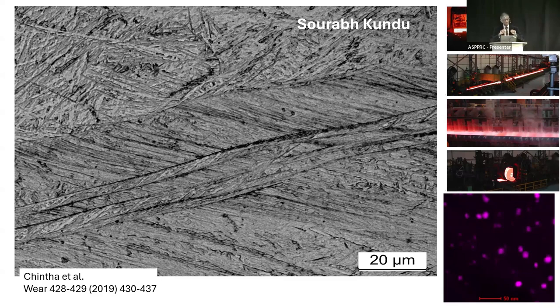You pancake the grains of austenite so severely that they look like this. And furthermore, you introduce huge numbers of deformation bands in the austenite. So the effective grain size that people have talked about, the coherent region of the austenite crystal, becomes extremely small. And you've introduced vast orientation gradients across the grain, and martensite cannot cross those boundaries, okay? So the martensite that you get is extremely fine.